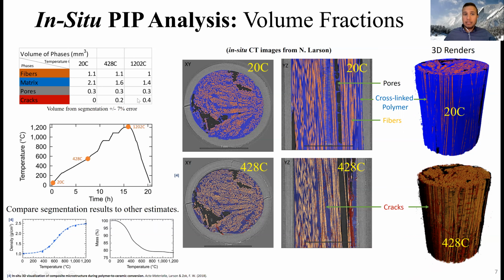And with these experiments at different temperatures, you can really relate these volume calculations from image segmentation and validate them with the measurements that Natalie has gone through, for example, density measurements, as well as mass percentage loss during pyrolysis. So volume fractions can be useful.